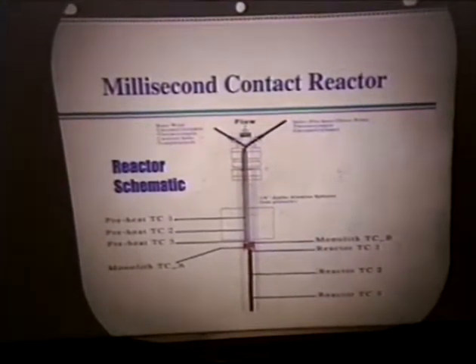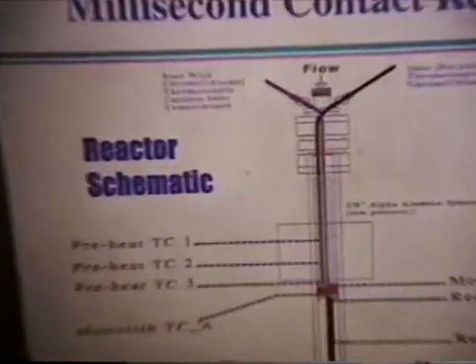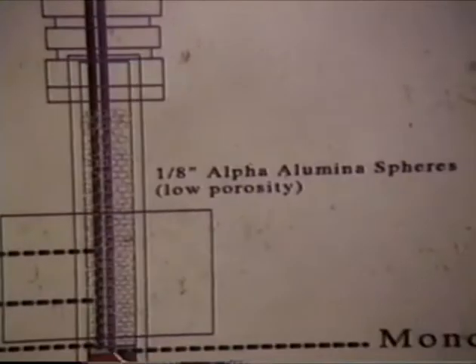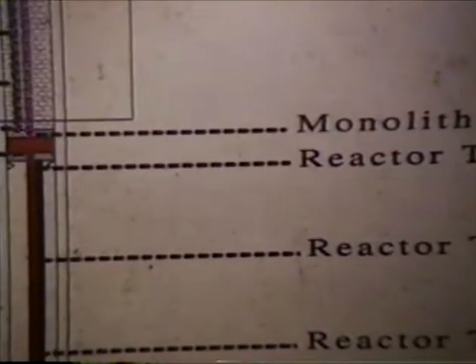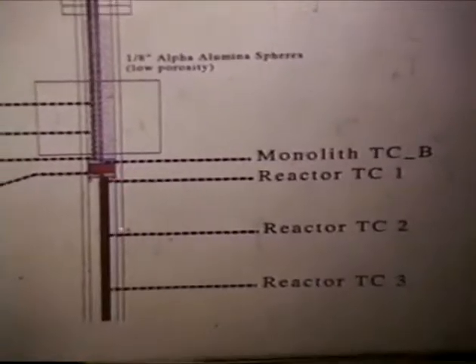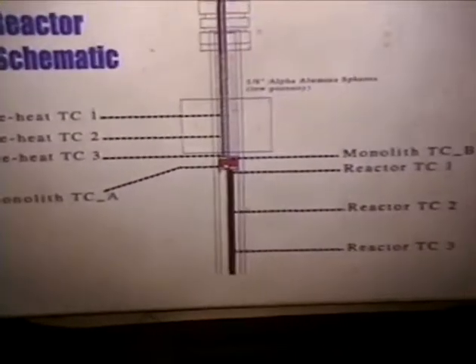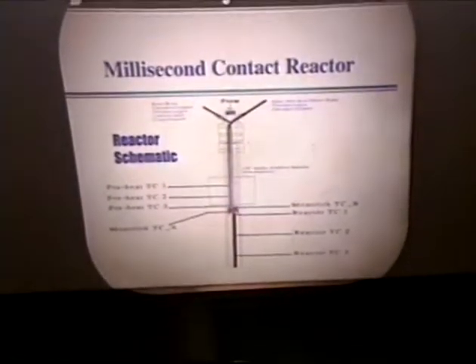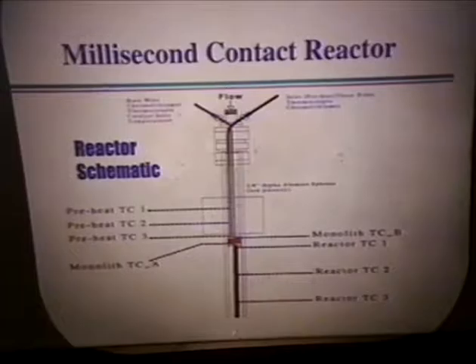And schematically, it's a little easier to see what's happening here. You preheat in this zone and pre-mix your feed, monitor your temperatures, sandwich your monolith in between two heat shields, and then monitor your exit temperatures. You want to cool down as quickly as possible below the heat shield.